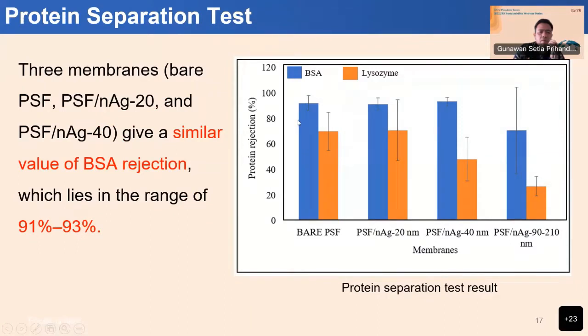it's not so different between the pure membrane and the membrane with the nano additive powder here. So we can see that it's almost the same and gives a similar result. It means that it doesn't really change the pore size of the membrane much. And the rejection of the BSA lies around 91 to 93%.